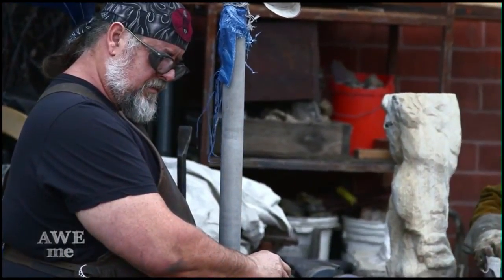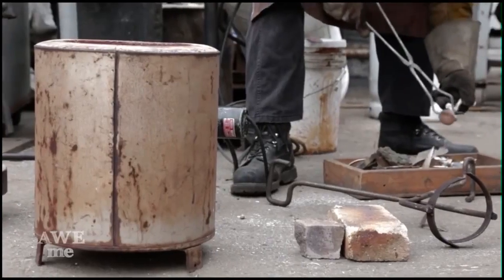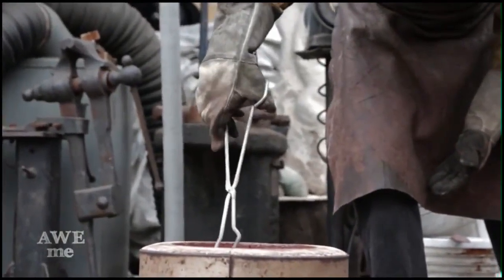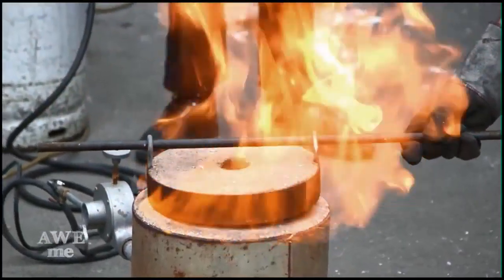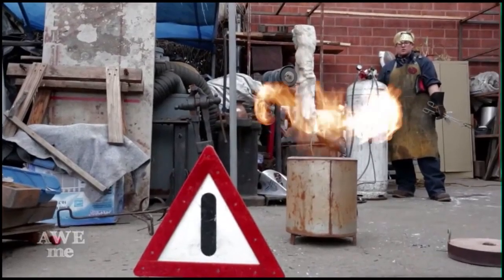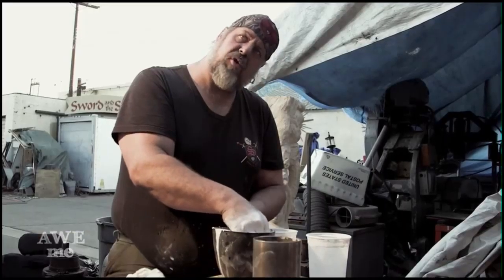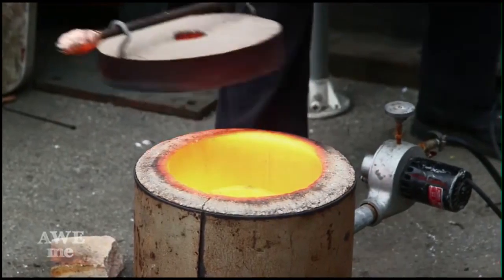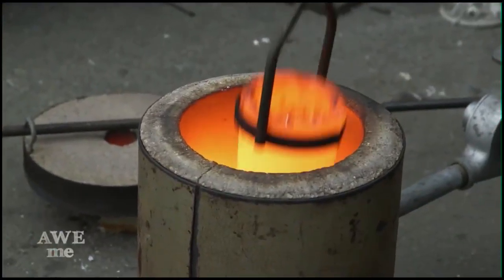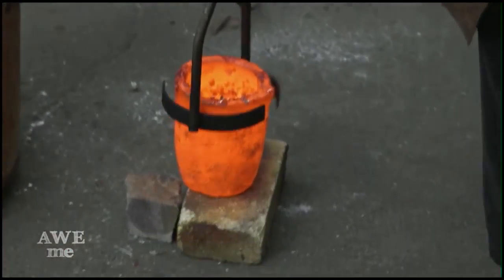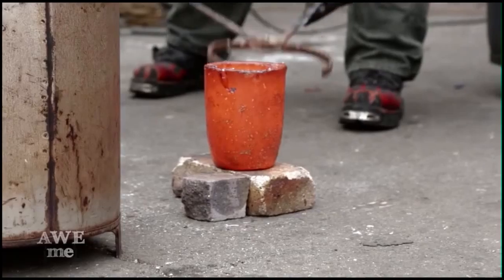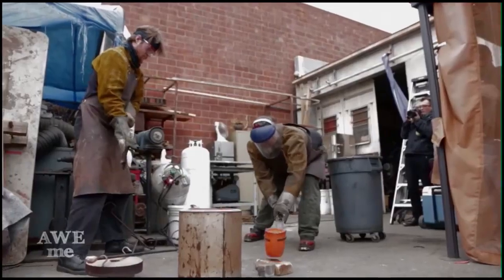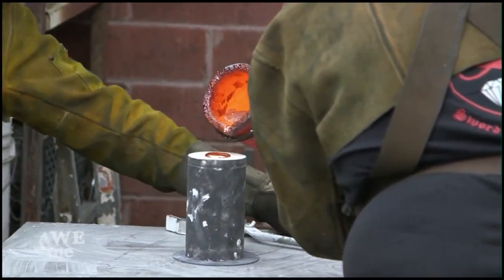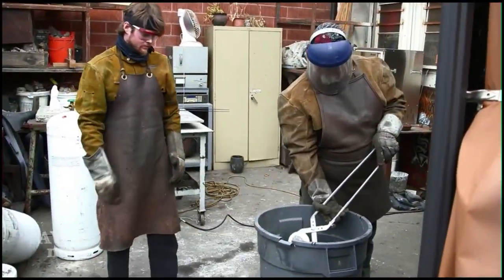They used to do this in ancient times using beeswax to make the mold and clay to make the investment, and then they would melt the beeswax out of their mold and pour molten bronze or gold or silver into it. We'd melt the bronze in a crucible inside of the melting furnace and pour the molten bronze into the flask while a vacuum was pulling from underneath to give a nice dense casting.